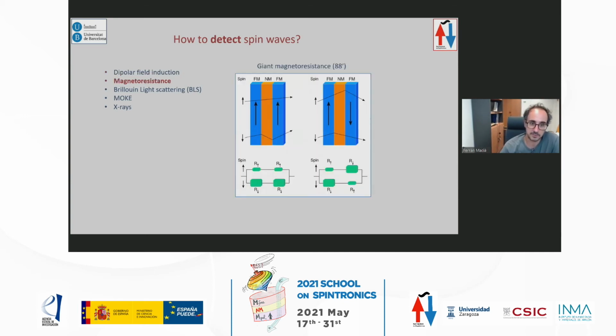We can use magnetoresistance. Giant magnetoresistance tells us that if you have the reference layer, and you have an excitation here, it means that you're changing the effective length of this magnetization vector. So if you read the R versus T, you will get an oscillation. This is one of the ways to detect spin waves, but you have to make a point contact and pass a little bit of current to measure the resistance.